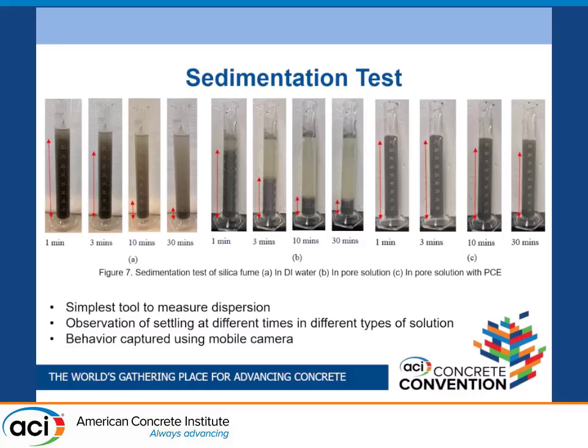Then we quickly transfer it to a 100 ml graduated cylinder, and note down the time for 1 minute, 3 minutes, 10 minutes, and 30 minutes, letting the sample settle without disturbing it, and visually capture the sedimentation rate using the camera of a mobile phone.